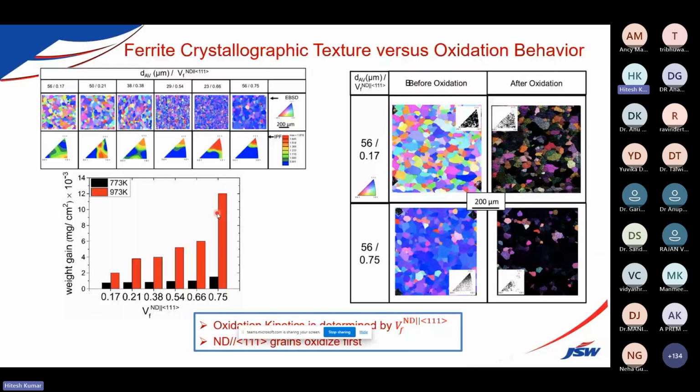We also did Raman spectroscopy on those grains. As the literature suggested, the first oxide grains forming were magnetite, Fe3O4. That is also confirmed with the Raman.